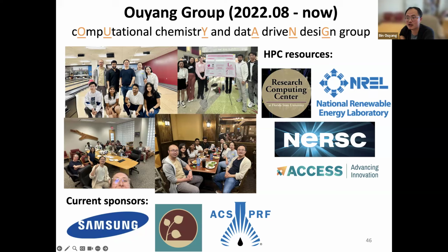The second thing is that we are also working on meta-GGAs. We spent quite a few years collaborating and talking with experts in this field, like Professor John Perdew and his student Jianwei Sun at Tulane University. He's actually the developer of r2SCAN. Part of our database is based on r2SCAN, because it effectively solves the problem of the formation energy without any correction.